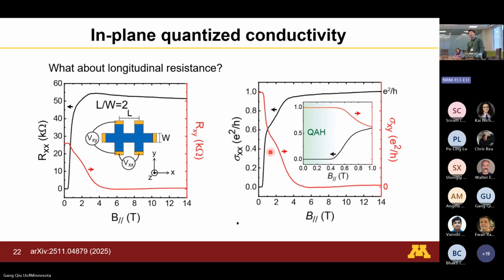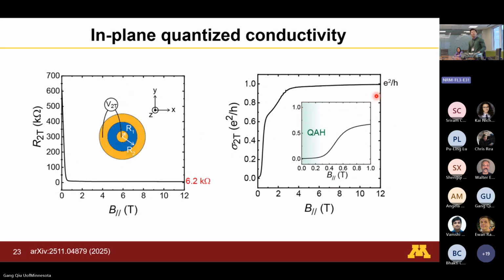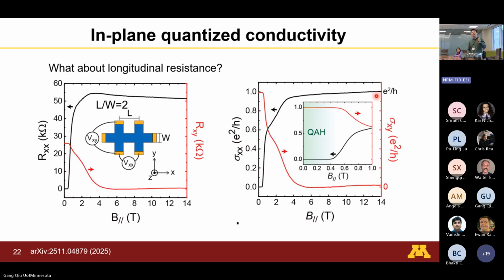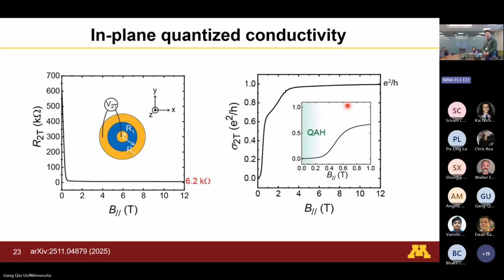The 1/2 plateau is something that we expected when we do this experiment. We're just looking for that. But this is completely out of expectations. We don't know where that comes from. We just wanted to make sure it's not some random lucky scenario, that somehow this thing saturates at this number. So we tried samples with different geometries, different aspect ratios. They always settle at this value.